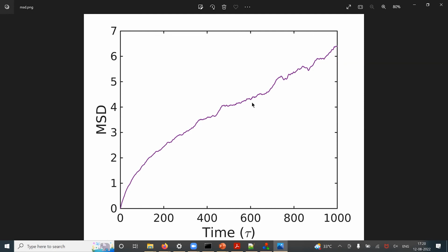So liquid structure is not defined, right? Basically you have to equilibrate the system. So if you just go beyond the melting point, you're starting the liquid structure, it will not be equilibrated because it's not under thermodynamic equilibrium at that particular state. So you need to run, let's say, NVT simulation at that particular temperature for a few nanoseconds to equilibrate your liquid structure, and then use that as your input for further simulations.